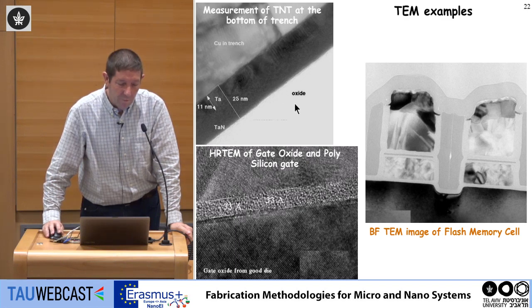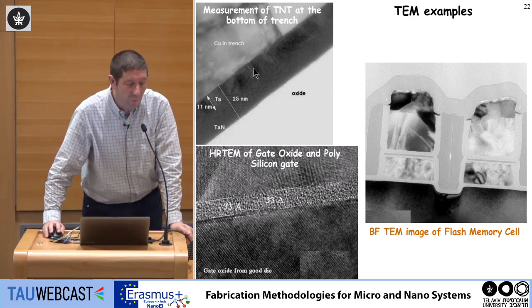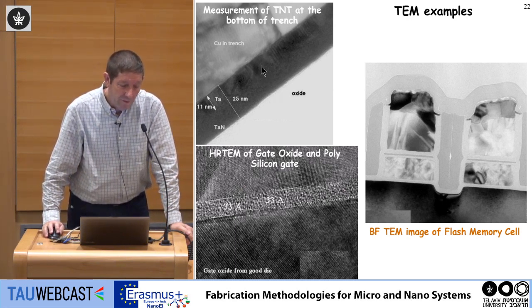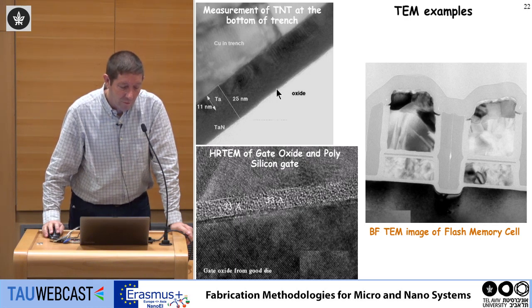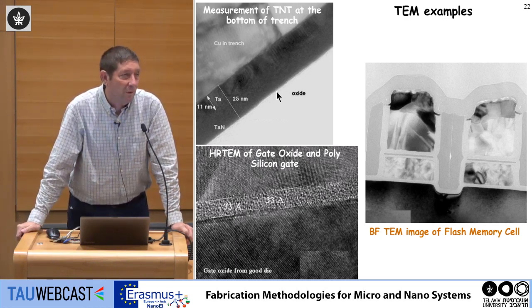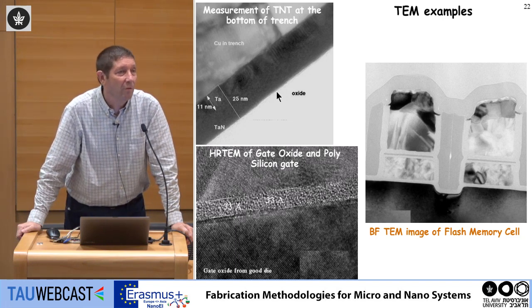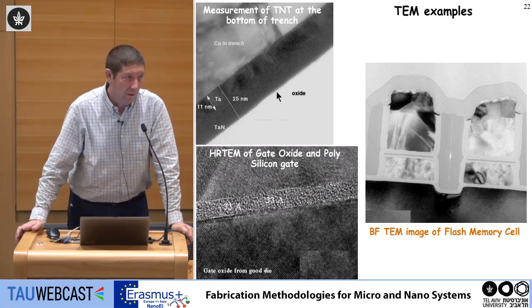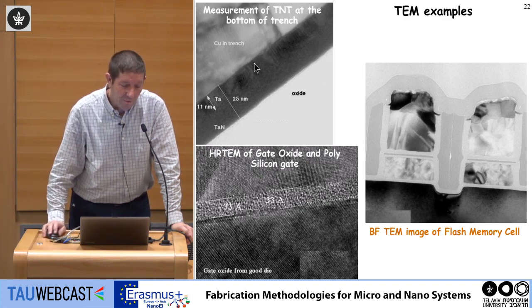You don't want to put copper directly on oxide, so you put a barrier layer. And tantalum nitride is one of the best barriers that is known. But if you want it to stick nicely to the copper, you have to put a very thin layer of tantalum on top of it. So tantalum nitride is one of the most common barriers today. The only problem with this technology today, you see this is 25 nanometers. So this is good for 65 nanometer, 35 nanometer technology. If you want to go below 25 nanometer technology, you cannot make the barriers so thick. The total should be less than 10.